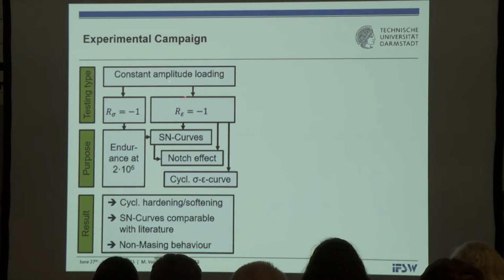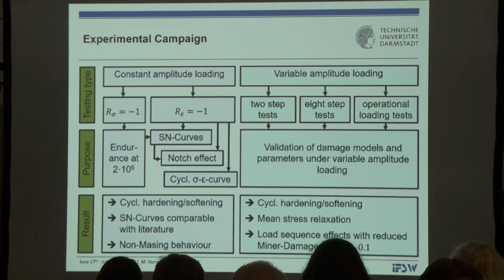So the constant amplitude loading provided us with SN curves and the notch effect and the cyclic stress strain curve and all these nice things, which you must know in order to perform such calculations. Also the cyclic hardening and softening of the materials and so on, and whether there is Masing behavior or not. And the variable amplitude loading tests have been taken to validate various damage models, and some of them I will report in a few minutes. You remember two-step tests, ordered 8-step tests, and random operational loading tests. And again, we measured cyclic hardening, mean stress effects, and Miner-type damages, which are going down to values of 0.1 only, meaning a factor of 10 on the unsafe side.